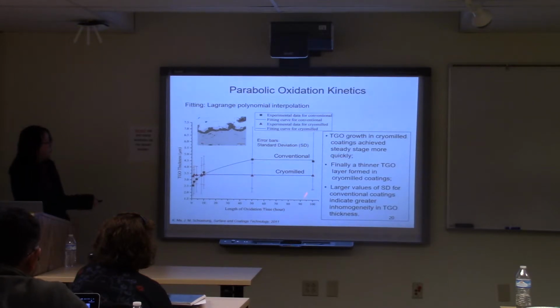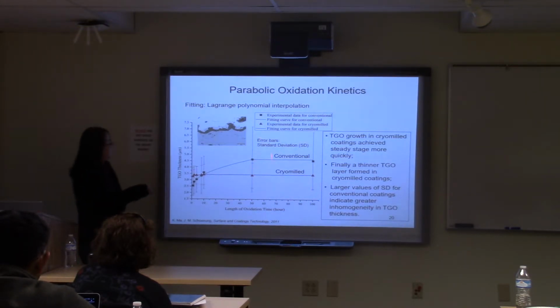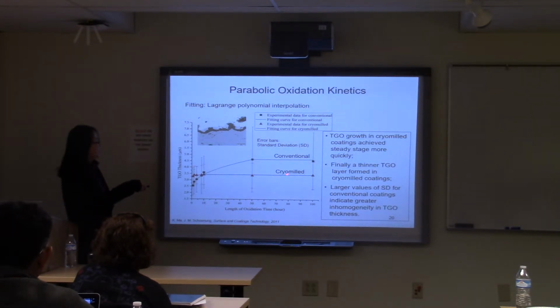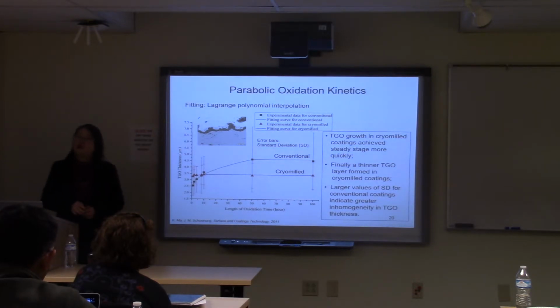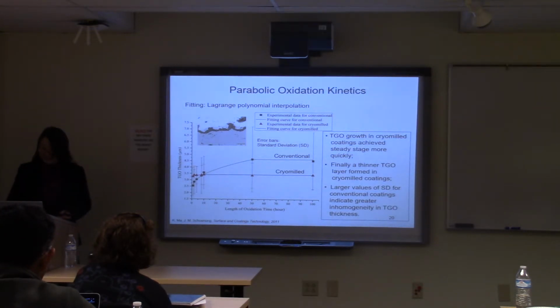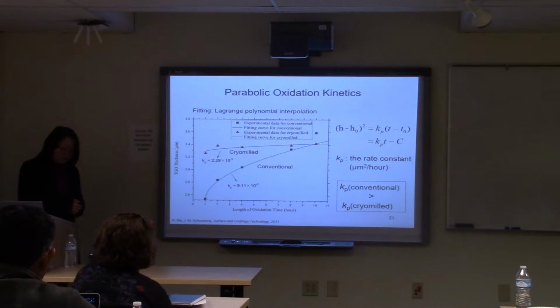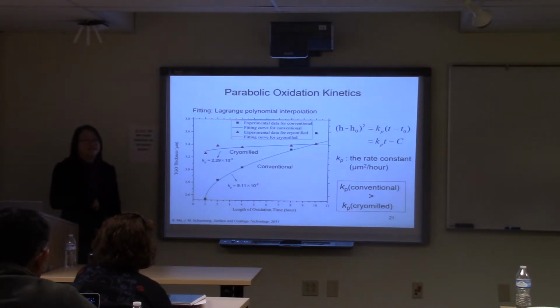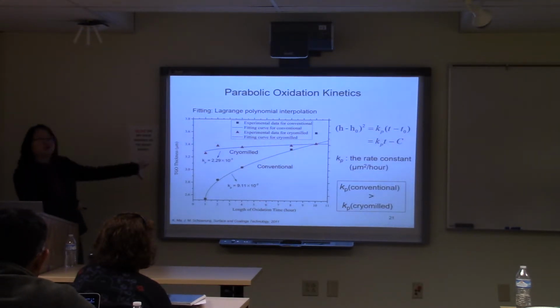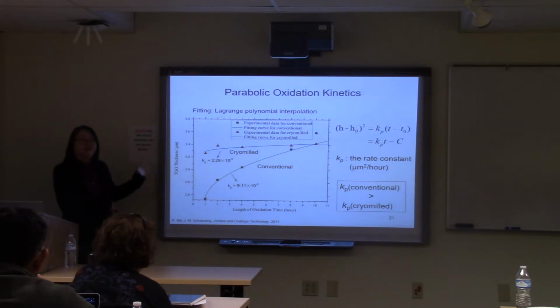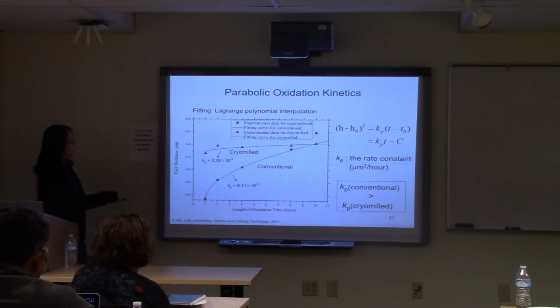And you also will see larger values, which is the red error bars here. For the standard deviation for the cryomilled coatings, it's smaller. So that means you get more homogeneous growth in terms of thickness. And then I look closer at the very starting point. So it's a zoom in of the previous figure, the very first 10 hours.